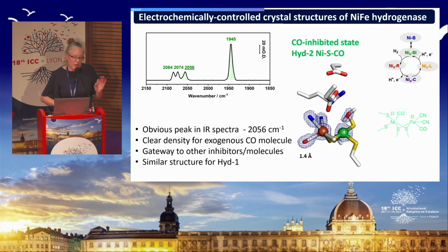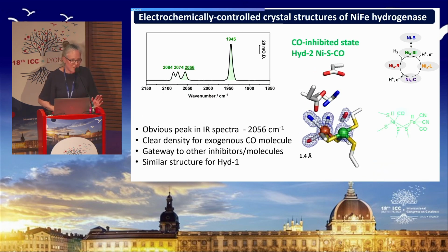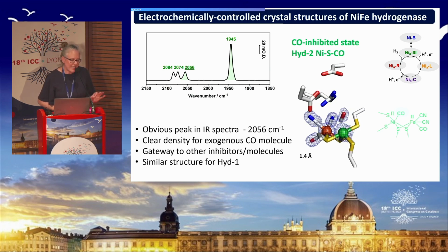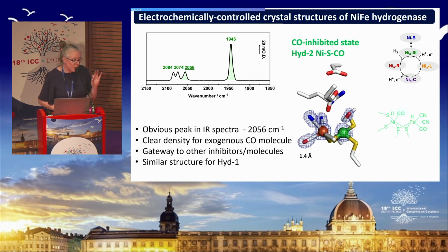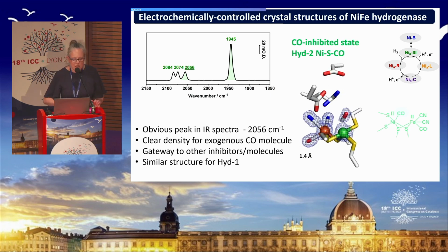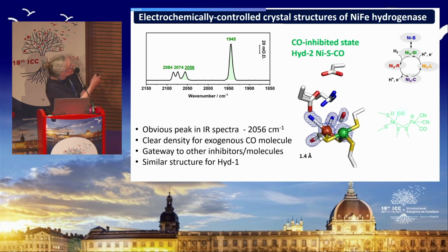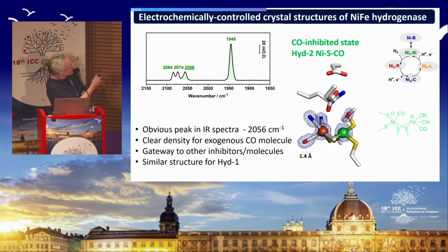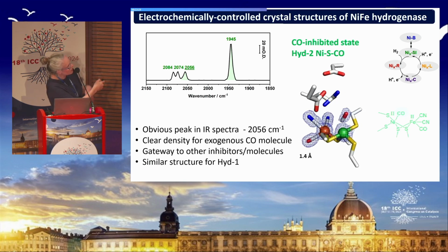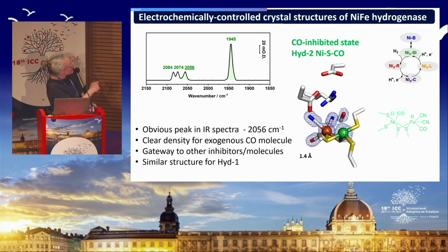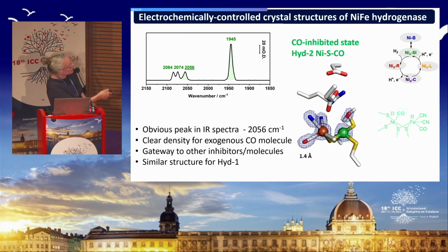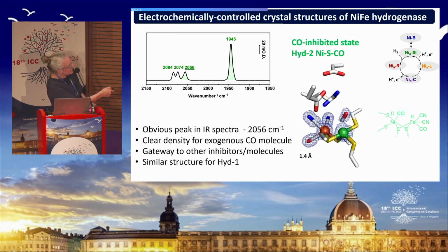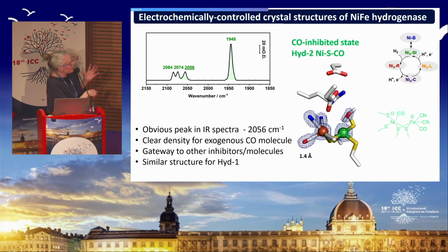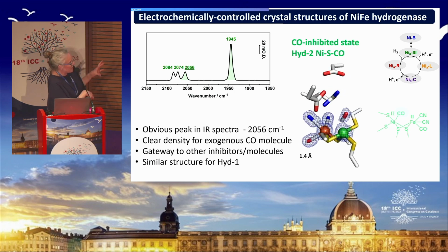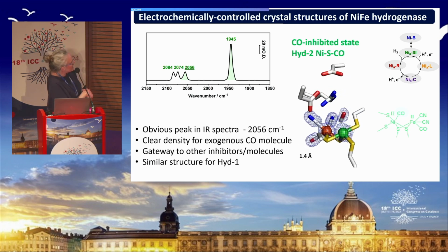So, to confirm, that was really at the nickel Si redox level. We reacted the crystals with carbon monoxide when we poised them electrochemically at that level, and we now have a very obvious extra peak in the spectra, which is consistent with the exogenous CO molecule bound to nickel that's well known, this CO inhibited state. And in the structure, we now have electron density consistent with the CO inhibitor bound to the nickel in exactly the position that would be expected and has been observed in other structures for CO-bound hydrogenase.